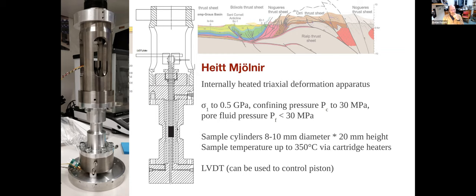Okay. So the challenge here is, in order to do that, you need a big fat pressure vessel. Well, that's something we cannot afford because we need to see through the pressure vessel. So we need to keep our pressure vessel as thin as possible while keeping it as strong as possible. And the way to achieve that is by really putting an emphasis on the temperature management inside the cell. So while the temperature is actually 350 throughout the sample and the thermal gradient is less than 5 degrees over 2 centimeters, which is a fantastic figure, the temperature here on the inside of the pressure vessel is never more than 100 degrees Celsius.